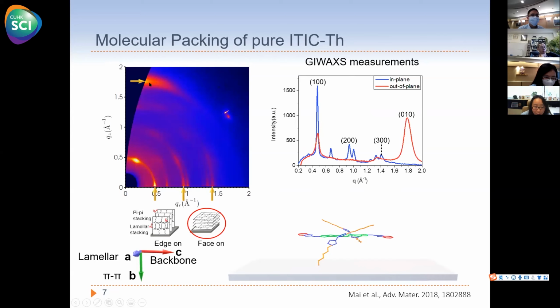You can see this peak on the Qz axis, which corresponds to the pi-pi stacking. The pi-pi stacking of the conjugated backbone is a relatively small feature, so it appears at large Q. Then the lamellar stacking peak corresponds to the conjugated backbones separated by the side chain, in this direction. So when we see the lamellar peak on the Qr axis and the pi-pi peak on the Qz axis, we know the orientation of this molecule is face-on, not edge-on.